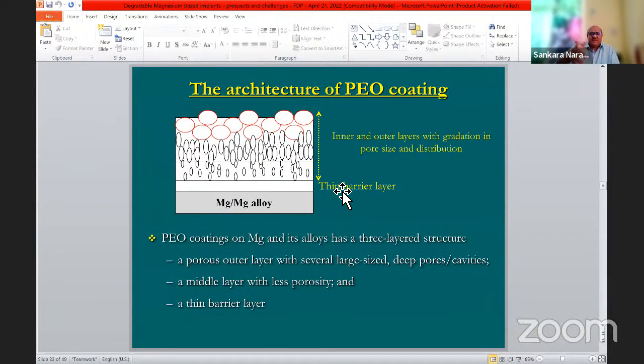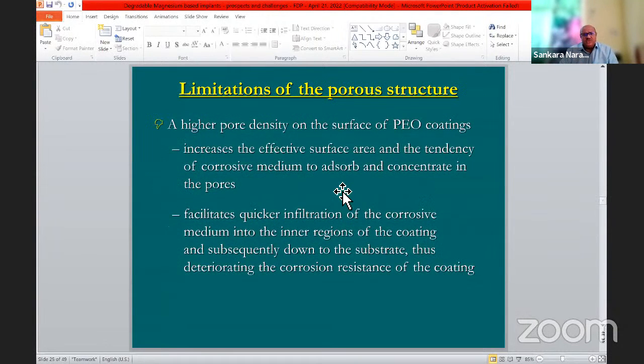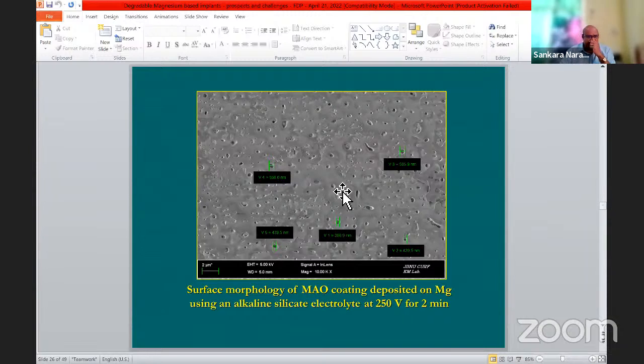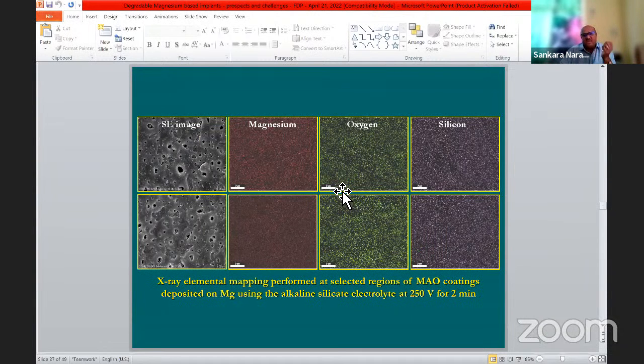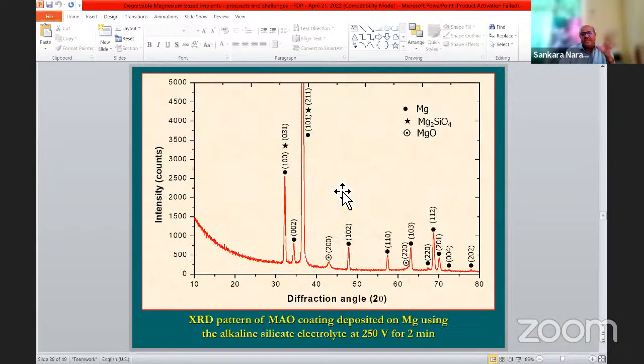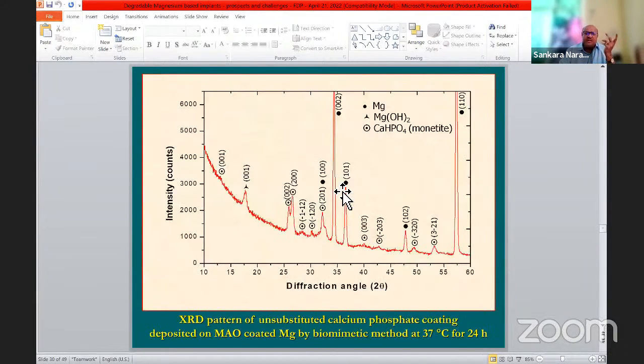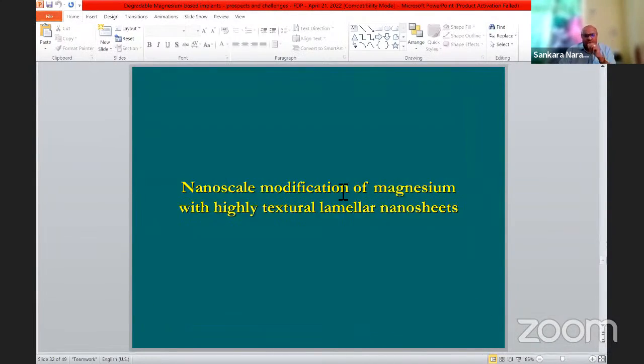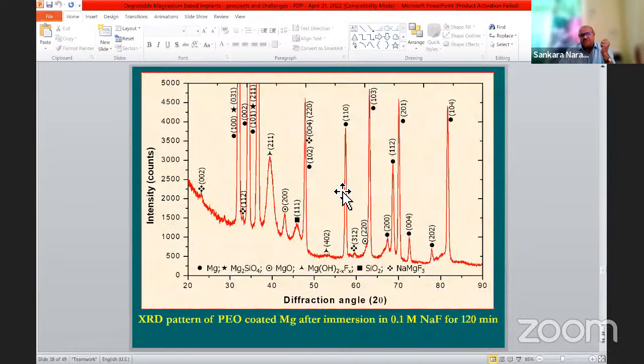Basically, this is the architecture. This has a thin barrier layer over which it forms a porous structure. This is the scanning electron micrograph of that, and we have analyzed the X-ray element mapping. Basically, it consists of magnesium, oxygen, and silicon, the silicate electrolytes. So this is the idea that we have developed different materials and coatings, nanoscale modifications and other things.